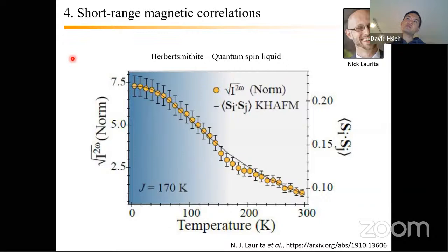Our setup is done with a pulse laser just to leverage the strong electric fields. It differs a bit by experiment and what each material can handle, but we typically use just below maybe a milliwatt average power, which corresponds to a fluence of just under a millijoule per centimeter squared, something in that range. We try to ensure that there's no pronounced average heating. We can do that from calculation, but we also look at some established phase transitions and see that they're not drifting too much from reported values. Does that answer your question?